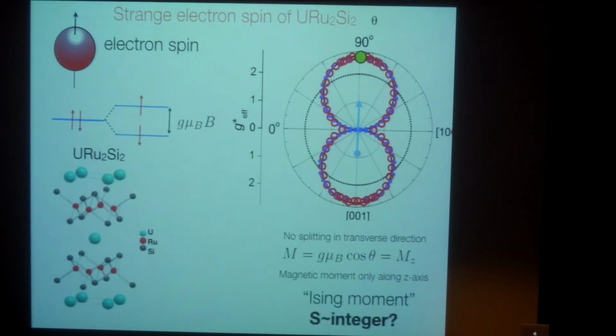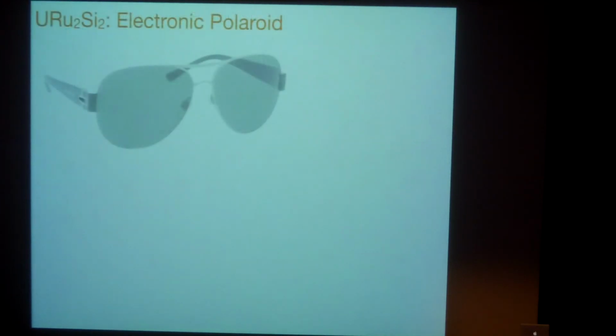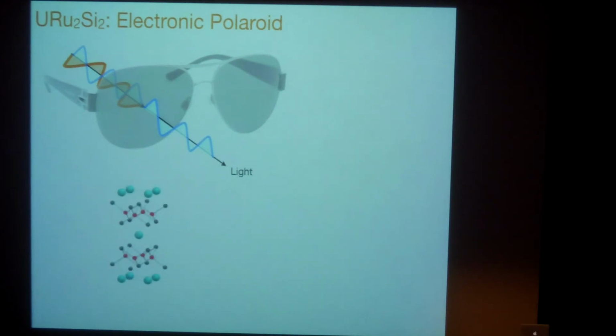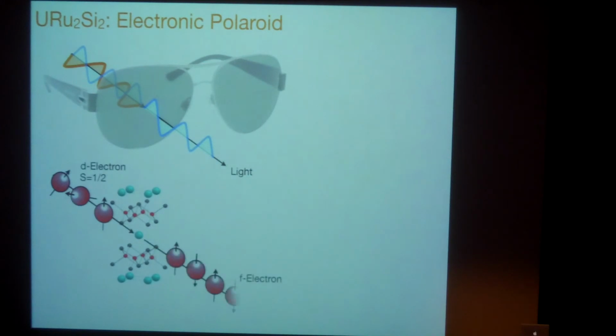And that this order parameter, just to finish off, is like an electronic Polaroid. Just as in a Polaroid you can polarize light, we think that the d electrons in this system, as they hybridize with the f electrons, are somehow acquiring integer spin character. And if they've got an integer spin character, that means the order parameter that links them has to be half integer. And so that's the idea that it might be a spinor.